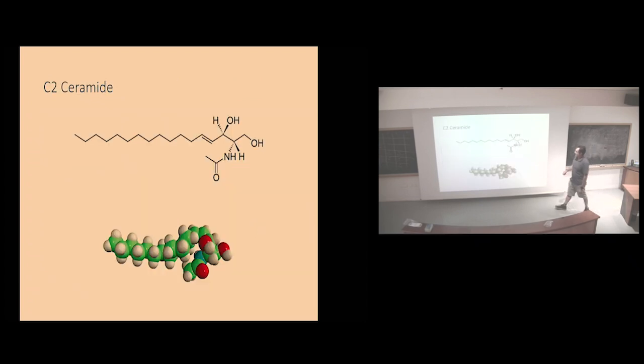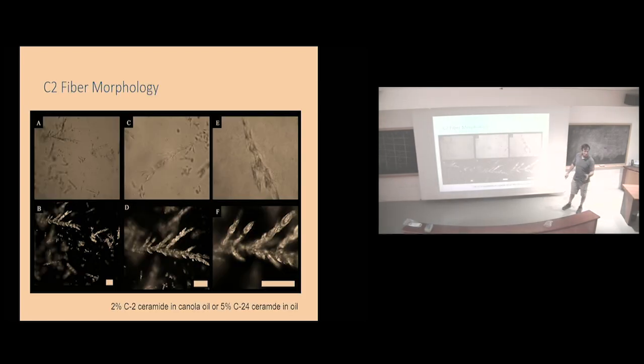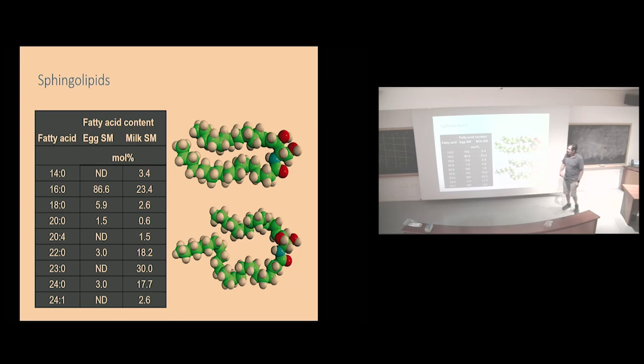So this is the C2 ceramide, in which we only have an acetic acid instead of the long fatty acid over there. That's how it looks, and we actually can form weird oleogels, but you can make a tree out of it. A little on the brittle side, I would like to say, but interesting. And then you saw those fibers with the pure components. So when you have a homogeneous system, one molecule, you form these fibers, right? But then you have egg, and there's ceramide in egg, and look at all the fatty acids that are present there. That's the length of the fatty acid. Don't even go there, like 23:0, 24:0. It's just a mishmash of different fatty acids.